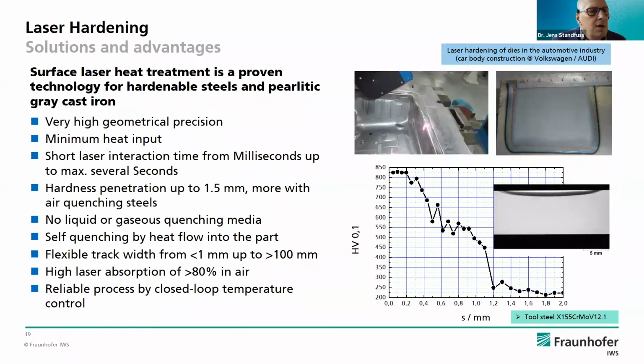What it means, only some slides here. The hardening depth for laser hardening is normally up to 1.5 millimeter, and I think with this hardening depth you cover a wide range of applications for gears, for stamping parts, for tools, and so on. The advantage compared, for instance, to induction hardening is that you need no liquid or gas as quenching media. You use the self-quenching of the part, of course, to minimize heat input only on the surface. And so you get the maximum hardness, shown here for tool steels, over 800 Vickers hardness. That's approximately 62, 63